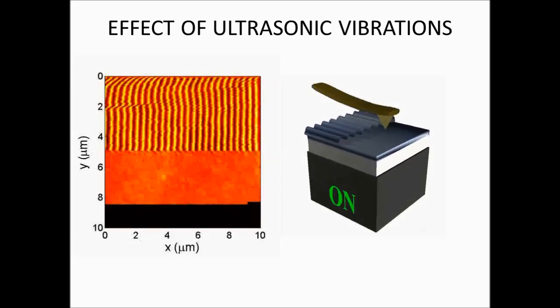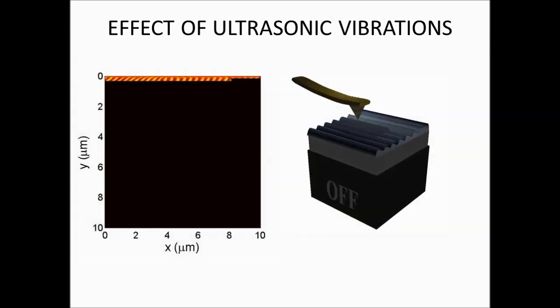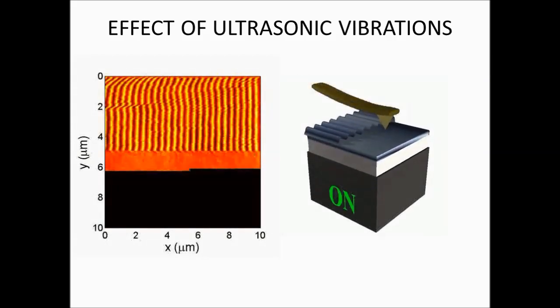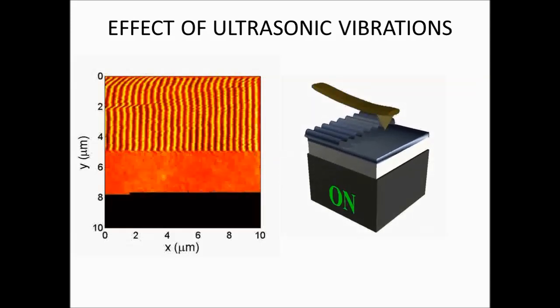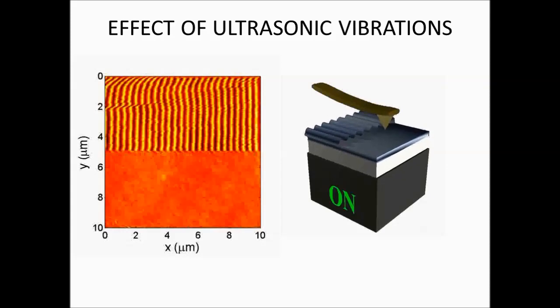Ultrasonic vibrations reduce such wear of the surface by facilitating a slip in each retracting phase of the vertical vibration. In addition, suppression of wear may be aided by the so-called strain hardening. That means a hardening in the plastic region of deformation, at large deformation and for high deformation rates.